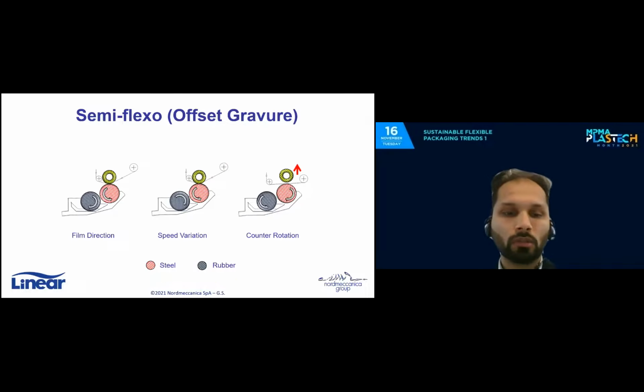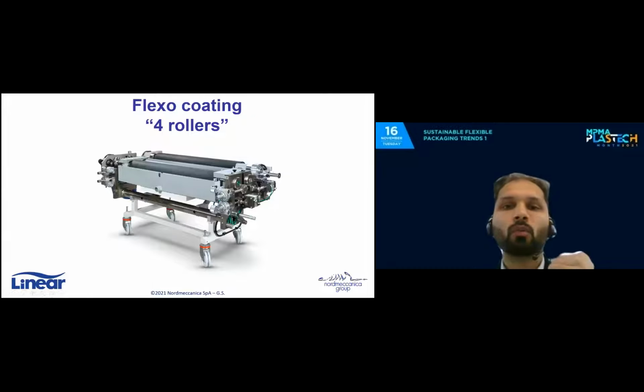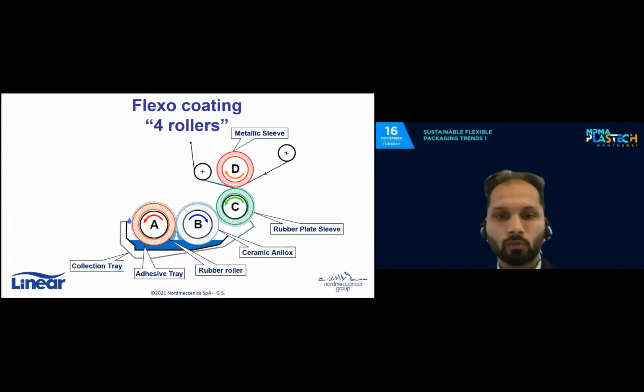Here you see the beauty. So this is what we have just described. If we play with the speed, we can change the coating weight. And with the Semiflexo, it's also possible to work in counter rotation in order to apply higher coating weights. Apart from the Semiflexo, we also have in our portfolio the flexo coating 4 roller. And how do these systems work?